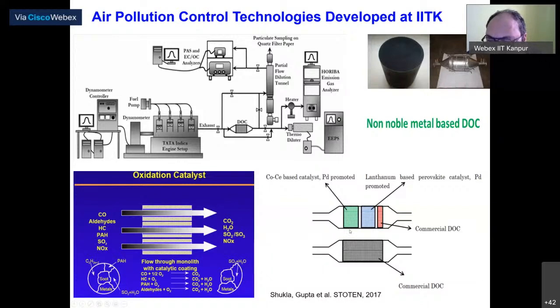whereas we wanted to cut down the cost of the commercial DOC, so we came up with two different catalysts. One was a cobalt ceria based catalyst, another one was a lanthanum perovskite based catalyst. Both use a trace amount of palladium as a promoter. This is the substrate, basically a flow through monolith structure, which after coating with cobalt ceria looks black in color. When we had a perovskite coating, it showed a gray color. The original parent color is cream. This is the housing in which the DOC was kept and tested. A part of the engine exhaust was passed through it, and then we had a partial dilution tunnel flow system where particles were collected on the filter. We had some real-time gas and particle measurement instruments.